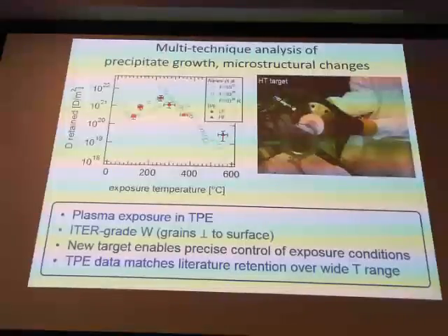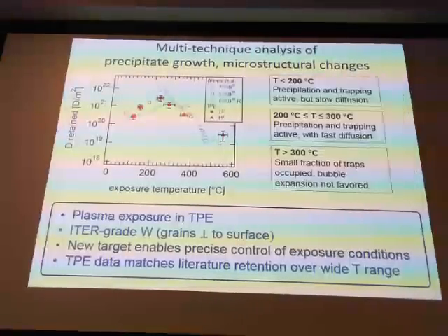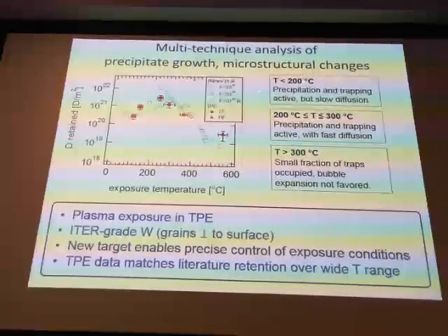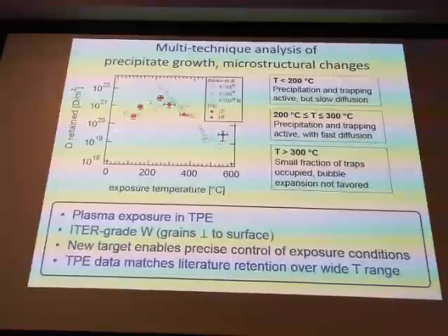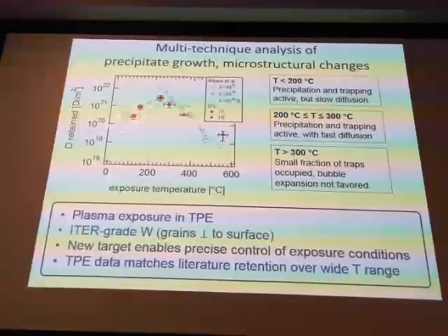And so what's responsible for this temperature dependence? Well, at low temperatures, it's thought that this bubble formation and precipitation and trapping are active, but you have slow diffusion, and so there's not deep diffusion of deuterium or tritium into the sample, and as a result, you have relatively low retention at these low temperatures.